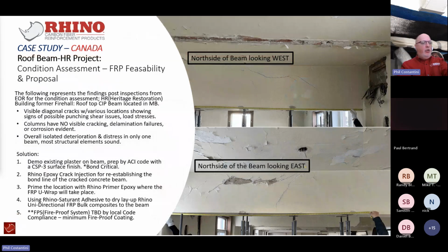Here's just a quick little case study. I'm going to share kind of what we do and how we do it. In many cases, we get approached by consultants and engineers all across Canada and the United States. In this case, this is a roof beam application where there was some cracking in one of the beams. Of course, the engineer of record immediately post-shored this beam, because the concern was the micro cracking going off on a diagonal in this beam out to the outside wall, or potential column or corbel detail to the exterior. Although there was no additional visible cracking anywhere in the exterior of the walls, it was primarily cracking in this one beam. It wasn't really overly distressed just in that one area, but most of the other structural elements were fairly sound.